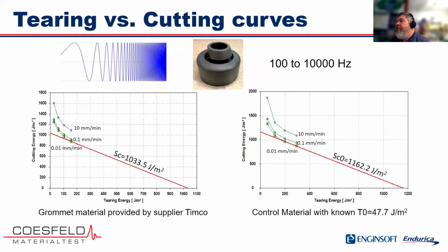So normally what we do is we'll run the experiment on a known control material that has a known fatigue threshold, and then we'll run it on the material that you want to use actually in your application, the feature material, and then we'll compare them. And that lets us calibrate for an absolute threshold value. So for example, in this case, this is a material that was provided to us for a grommet application.